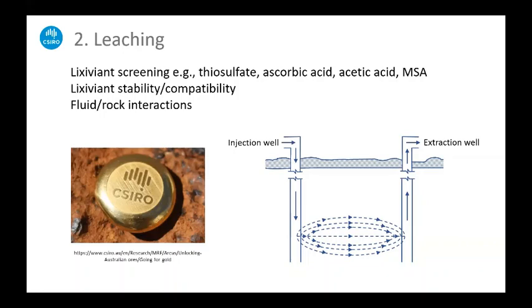And the image that you see, the photograph on the bottom left, is a commemorative gold ingot from the first gold pour using the cyanide-free recovery method. So thiosulfate is a potential promising reagent for gold extraction in situ from an environmental perspective. We've also looked at more unusual reagents: ascorbic acid, acetic acid, methane sulfonic acid. Some of these are proposed as more environmentally friendly reagents. Some of them might be more palatable for general consumption. So if you talk about lemon juice or vinegar, that's more understandable to people.